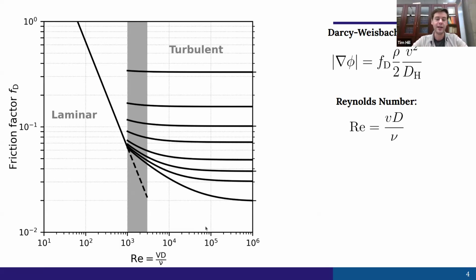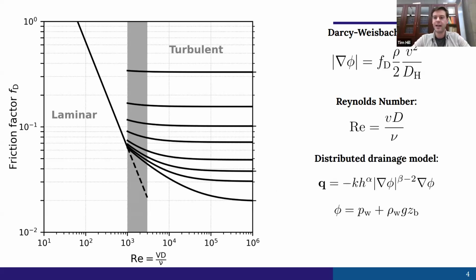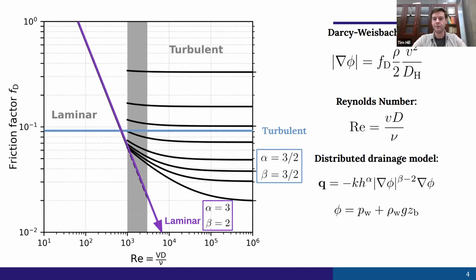What these experiments show is two totally distinct regimes. You have one laminar regime on the left, some sort of transition, and then a very distinct turbulent regime at higher Reynolds numbers. But what does the subglacial drainage model do? It has this other parameterization for Q here, which looks different than the Darcy flow law, but it can be cast in quite a Darcy-like way. In fact, depending on these free exponents, alpha or beta, you can get either turbulent flow or laminar flow, great. But one of the challenges is this has to apply across the entire range of Reynolds numbers, so you're not going to have something that's always self-consistent.